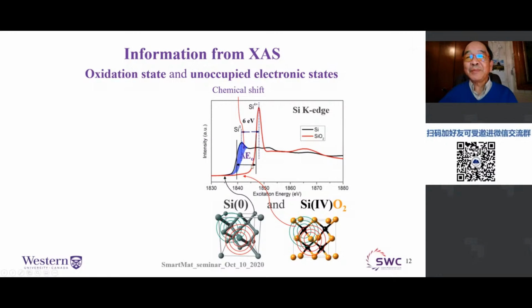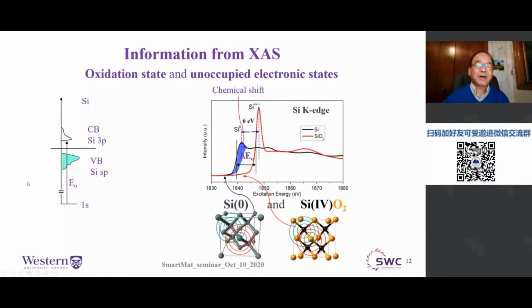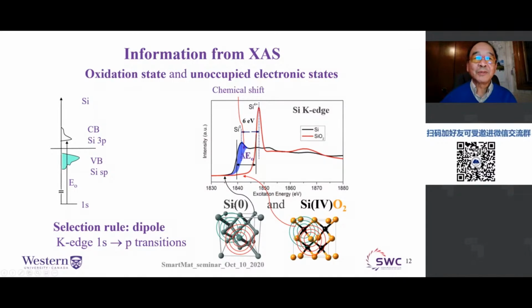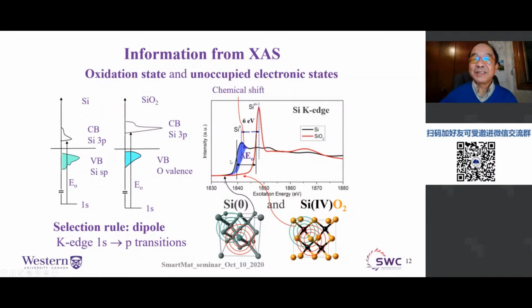Now, another thing is, you have a peak right at the absorption edge, and that's normally known as the white line. This peak, in the case of silicon, comes from excitation of the 1s electron into unoccupied p states in the conduction band. So we're actually mapping the density of states. And the selection rule is dipole, so s goes into p states and so on. In the case of silicon dioxide, obviously, the band gap is different and the density of states is different, but you're still doing an s to p transition.